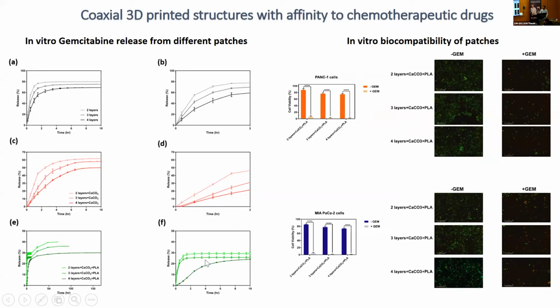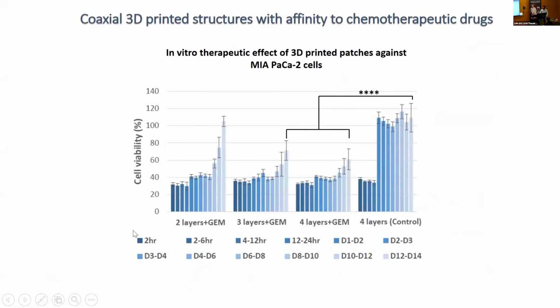And interestingly enough, you could adjust the release rate by adjusting the number of these 3D printed layers, like we 3D printed 4 layers maximum. We tested them on pancreatic cancer cell line, and they were able to kill the pancreatic cell lines in vitro. Then we've done prolonged in vitro studies on pancreatic cancer cell line MIA PaCa-2. What we've observed was that the 4-layer structure, all with calcium carbonate and PLA coating, were able to inhibit the cancer cell growth when compared to control samples that didn't have any drug in them.